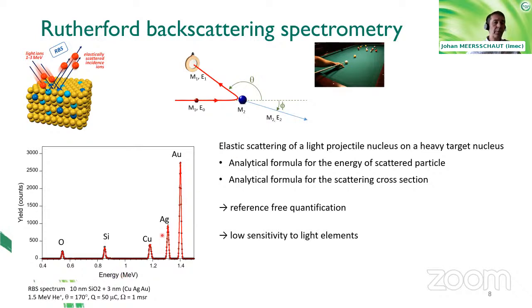You also notice in this plot here that the sensitivity to the light atoms is much lower as compared to the sensitivity to the heavy atoms. So you see that when you scatter on a gold atom, the scattering cross-section is much higher than, for example, the scattering on a silicon atom. This can be understood because the cross-section or the diameter of such a nucleus for gold is much bigger than the cross-section or the diameter of, for example, a silicon atom. So you might wonder how we are using these technologies.